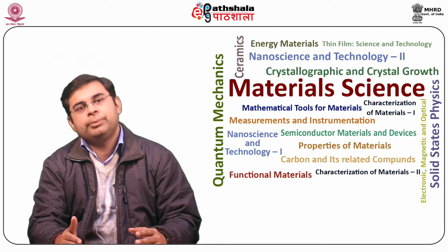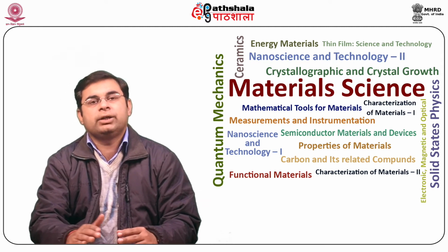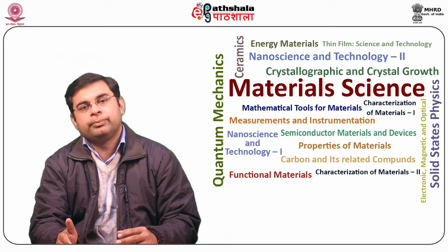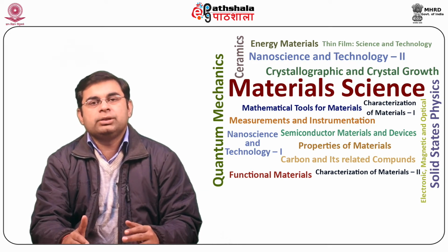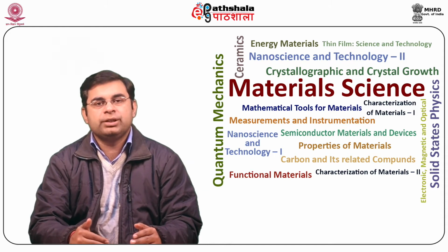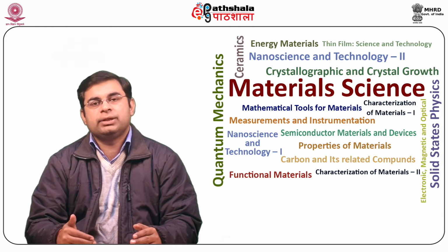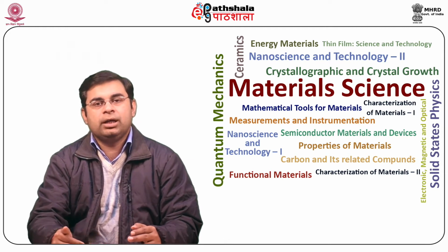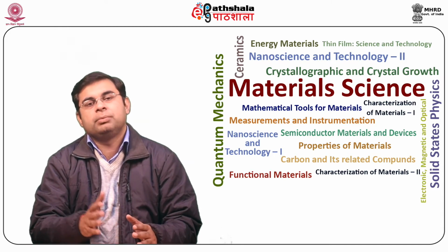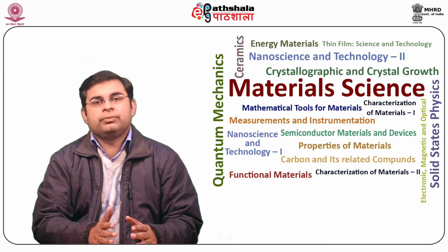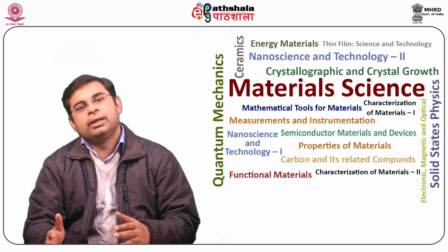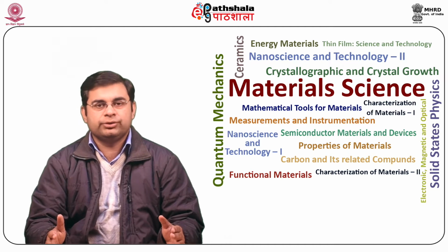The standard SRP technique cannot be used to characterize junctions that are less than 100 nanometer deep. In addition, the application of proper sample preparation technique and probe conditioning in connection with an advanced analysis of the measured raw data is required in order to obtain reliable results by SRP. SRP is rather time consuming and an intrinsic detection limit exists for low dopant concentrations.